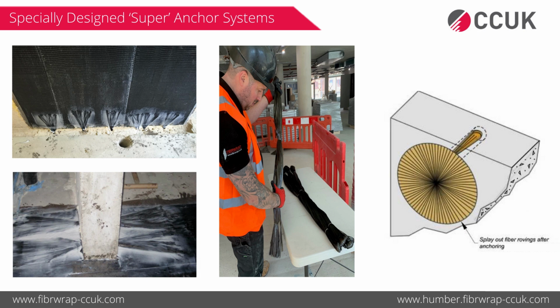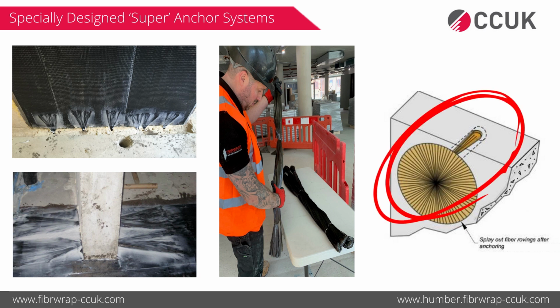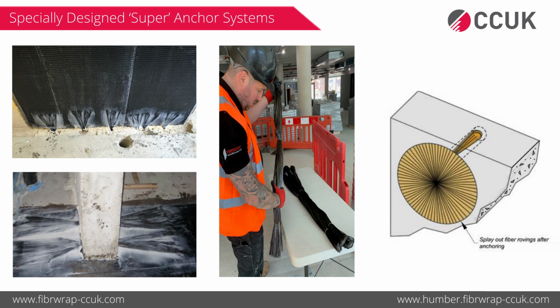Generally, there are two types of anchors. One is used for construction detailing, which we've seen, like the small anchors. Then we also have bigger anchors, which are specially designed anchors. For the small anchors, we drill a hole into the concrete, saturate the anchor, put half of that anchor into the drilled hole, which is filled with epoxy, and splay the remaining half on the face. After curing, it becomes one unit which cures simultaneously, but it is actually going into the concrete, so it provides you additional anchorage or bond capacity. So your debonding or delamination failure will not happen. That's how those nominal anchors are used.